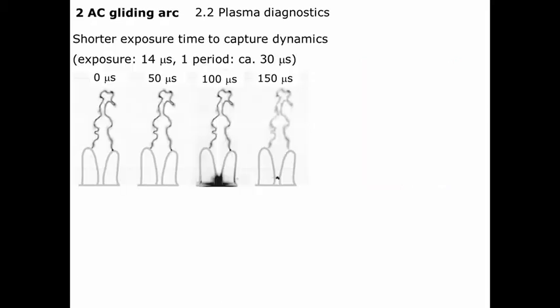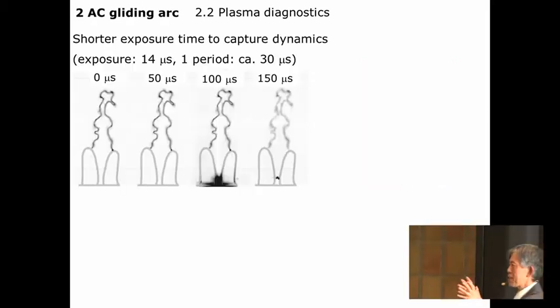Then I've been showing gliding arc photos with a kind of bulky discharge, but we tried with a short exposure high-speed camera measurement. Then we have seen something very different. It's in reality a kind of very thin, a few millimeters diameter, wire-like discharge. Since it is moving very fast, you can see the bulky one, but in reality it is thin.